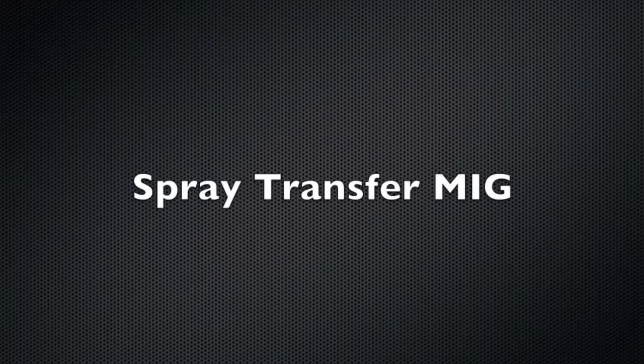All right, what is spray transfer? It's a different way that the metal comes off the wire. It comes off in fine little droplets, and it's really hot. It penetrates deeply, and it's mainly for heavy, thick metal and for production work. It's a prequalified process for doing code work, whereas short circuit requires you to qualify the procedure, and it's got a deep penetration profile.